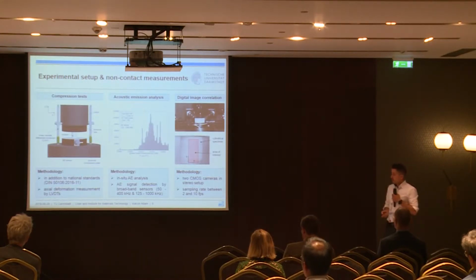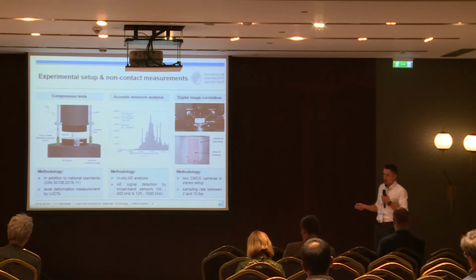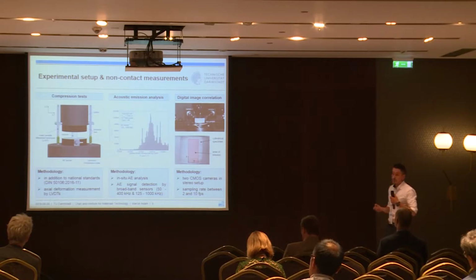That's the experimental setup we used. It's mainly based on a conventional compression test setup. We perform compression tests in accordance with national standards, measure the axial or longitudinal deformation of our cylindrical specimens, and we additionally equipped our test rig with acoustic emission measurement equipment.